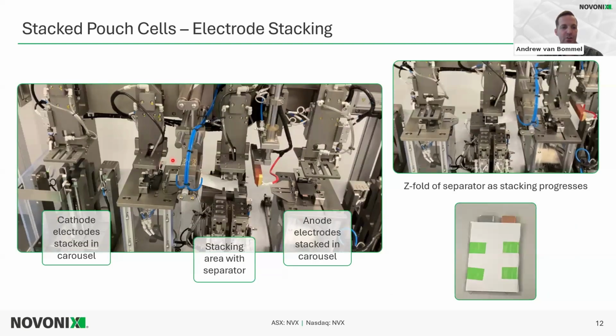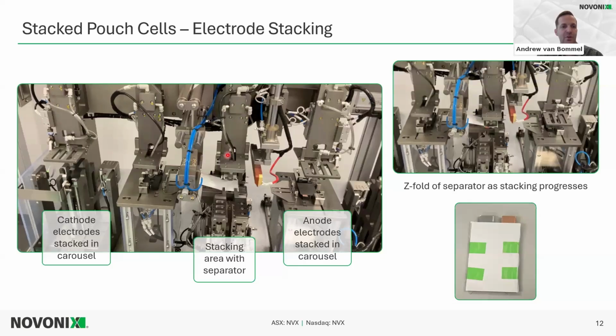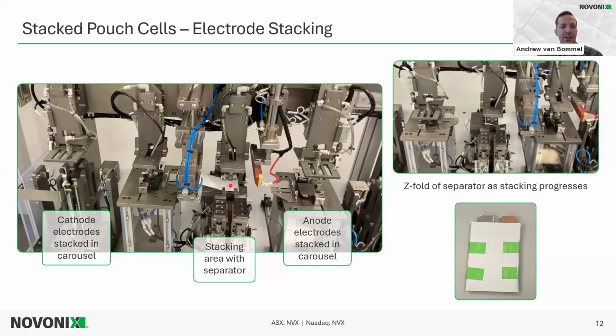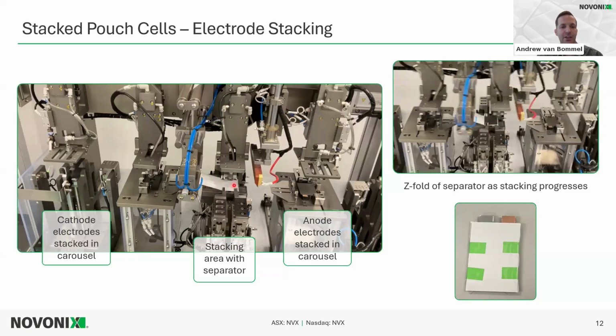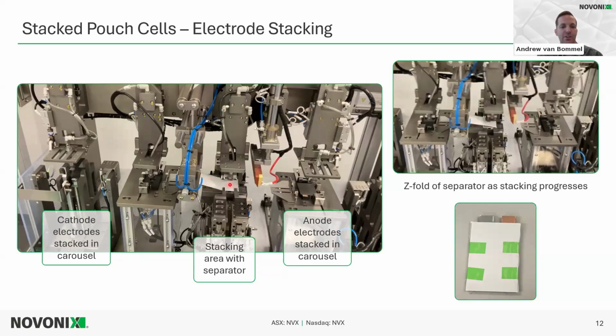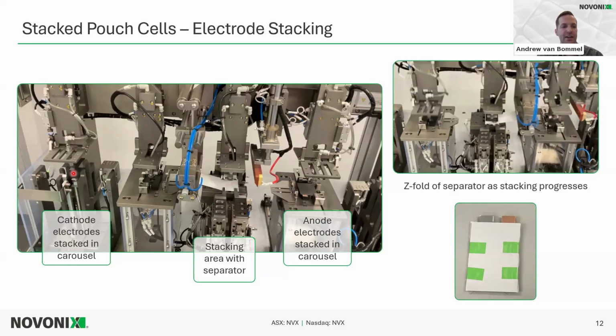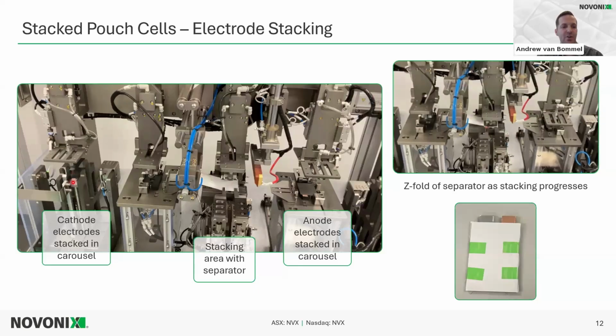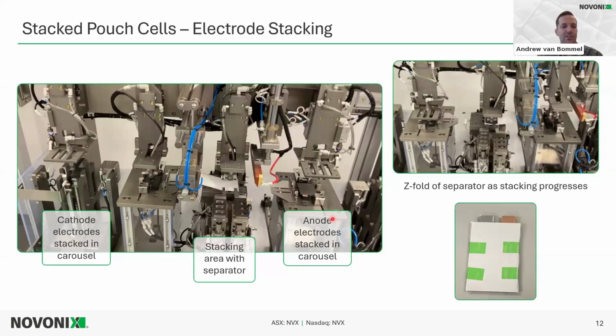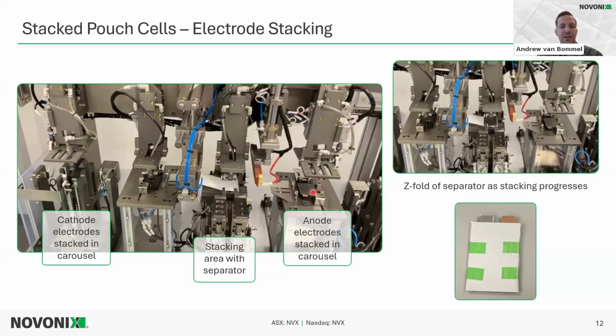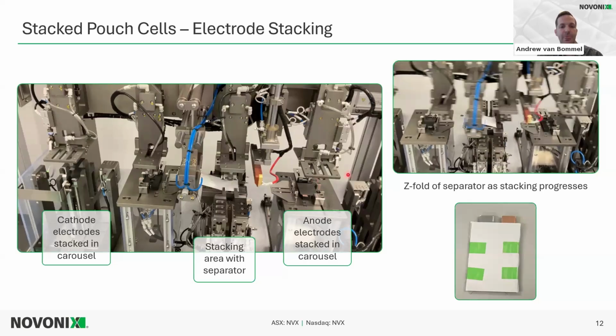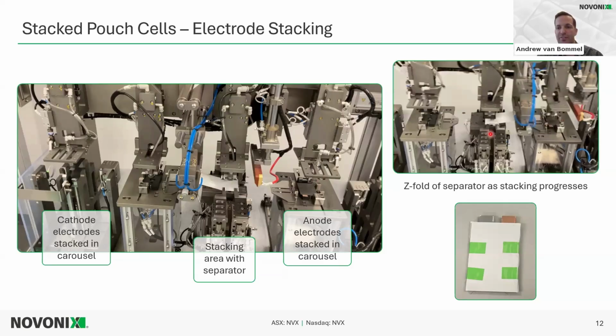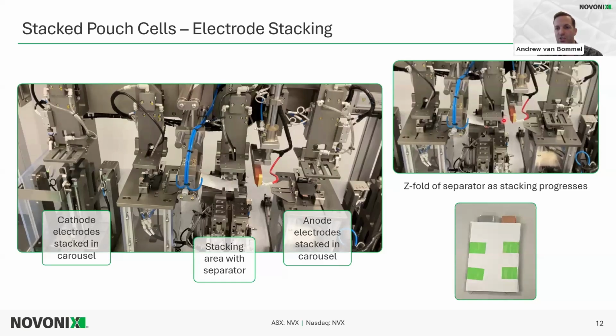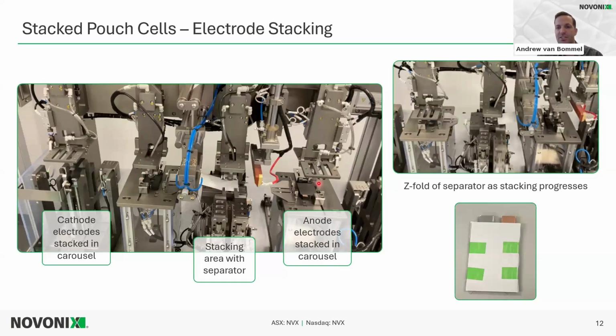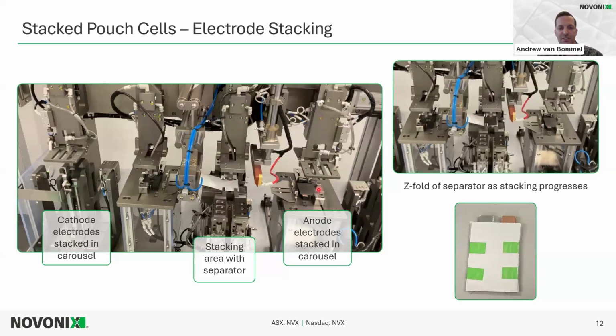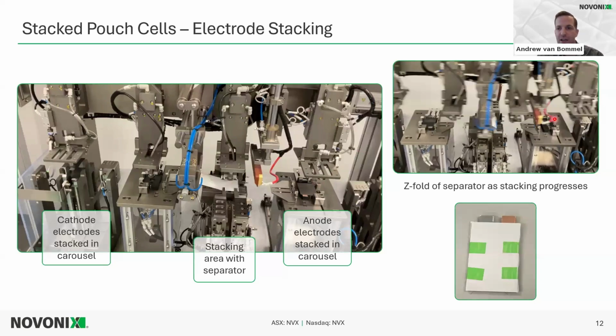So now I'll show the electrode stacker that we use. So the center area is the stacking area with the separator. So it has 1 roll of separator used. On the left, here's the carousel with the cathode electrodes. And on the right, here's the carousel for the anode electrodes. So the GIF on the upper right shows that stacking process. So suction cups, which are shown as I'm indicating right here, are used to grab that